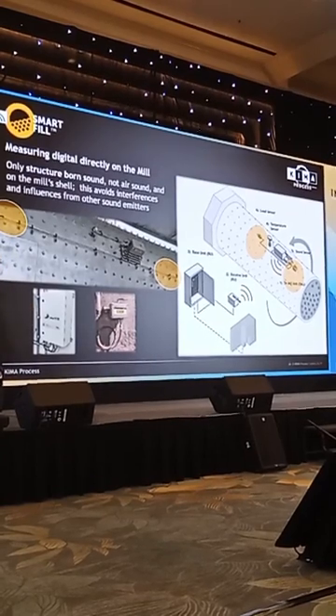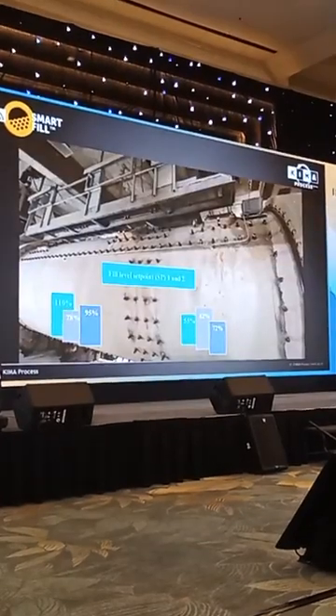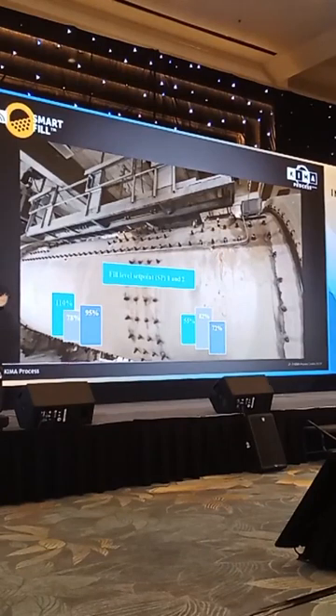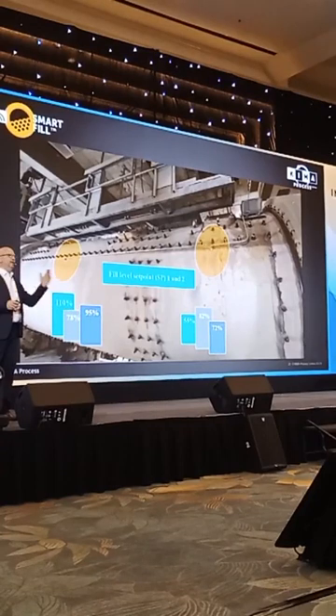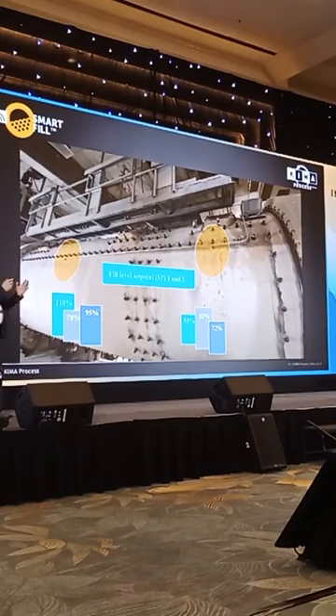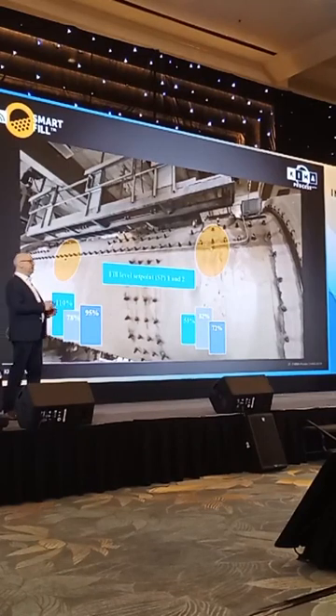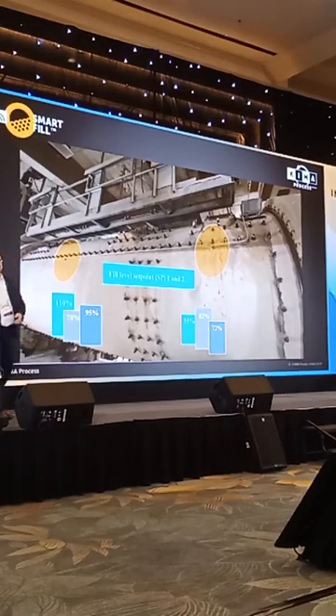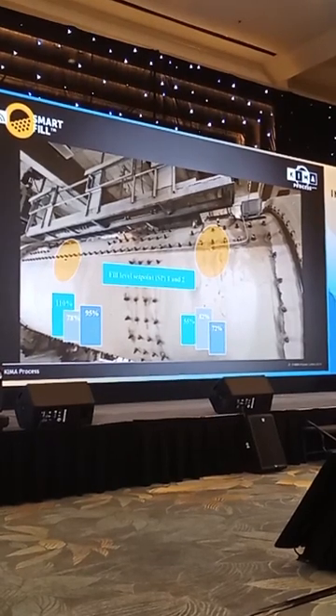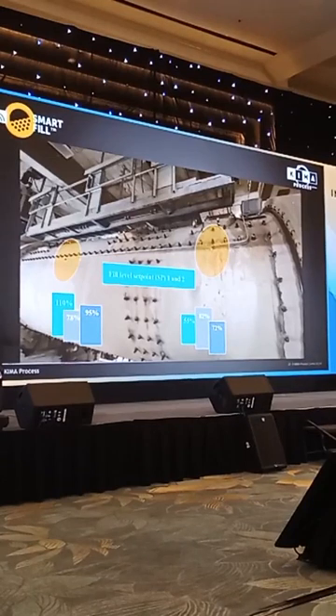I don't want to be too technical because you are more concentrated on the cost efficiency of production. Let me tell you only that with this instrument, you get the opportunity to find a so-called fingerprint for the optimum adjustment of the mill for each type of cement. When you change in your one ball mill from ordinary Portland cement to a fine cement, a slag cement or a limestone cement, this system knows in advance what the optimum adjustment is, and you don't have to wait for the laboratory values, which usually come 1 or 1.5 hours later.